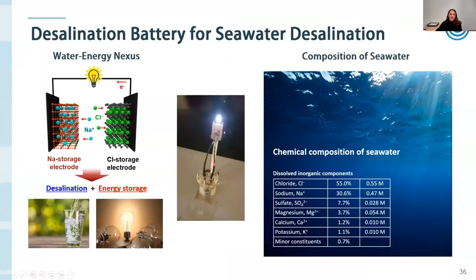And I like to show this image here from our lab taken a few years ago, where we immersed our nickel hexacyanoferrate and bismuth electrodes in a sodium chloride solution, and actually were able to see firsthand this power generation when we connected those electrodes up to a light bulb. This lasted for about 20 minutes, kind of a cool, fun benchtop experiment to do. And through the development of this desalination technology, we're combining the functions of desalination with energy generation and storage, trying to address challenges at the intersection of the water energy nexus, a mission that NAWI shares as well.